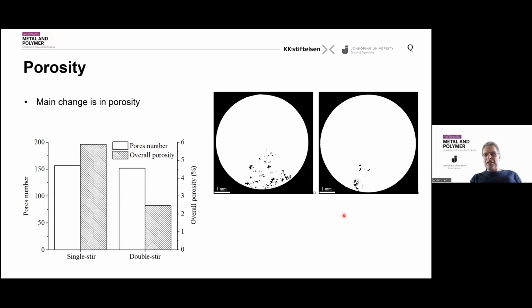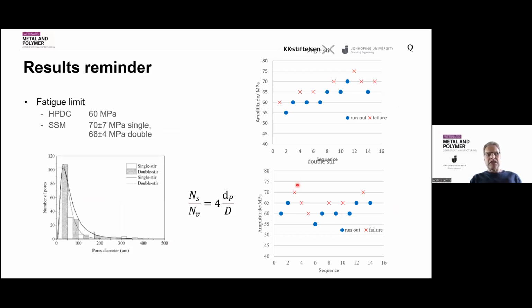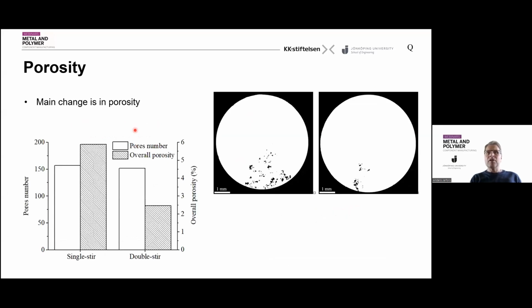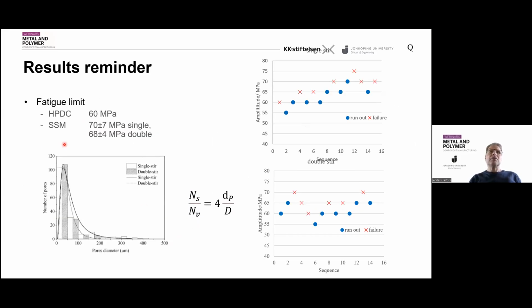Then we also did fatigue testing, and this was push and pull fatigue testing at 150 degrees centigrade, which was corresponding to what this type of component we had as a target was supposed to endure. And the high pressure die casting managed about 60 megapascals, while we got an increase with the semi-solid processed materials. And what we did was we used the staircase principle in order to establish the fatigue strength level here. Now, one thing which is important here is to say that there is not really any change between the semi-solid material with a single or a double stir. And this is, as you can see, the variation you see here. You have a reduction in porosity, so you have half the porosity. But it did not really affect the fatigue performance.